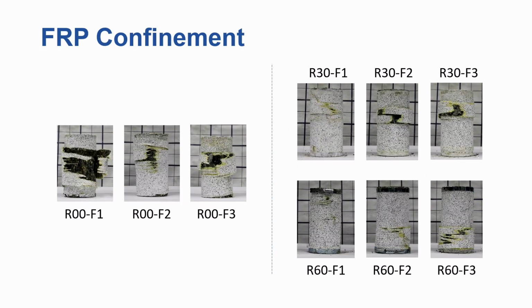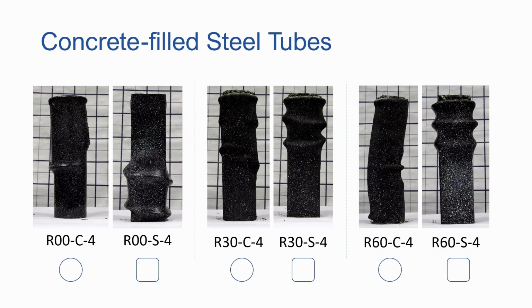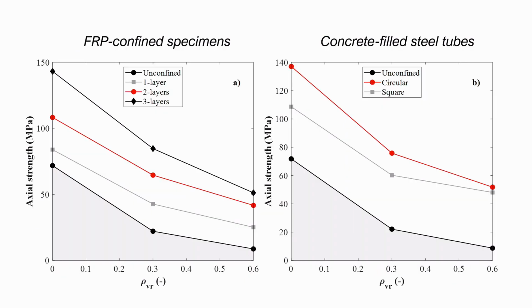So I'm showing here the failure patterns for the FRP confined specimens, that they failed by rupture of the FRP and crushing of the concrete. And these are the failure patterns for the concrete-filled steel tubes. They failed by, as you'd expect, buckling of the steel and crushing of the concrete. So these were tested under axial compression. And this just shows here the comparison of these.